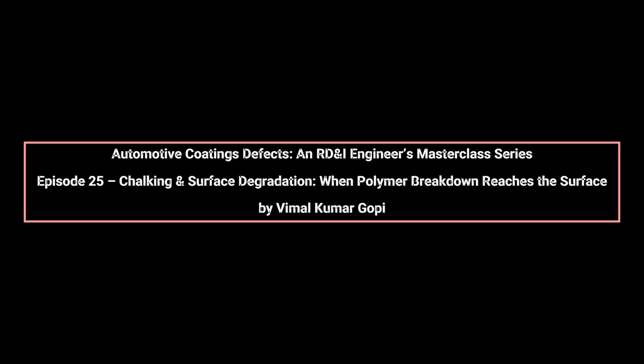Once chalking begins, protection is compromised. The surface becomes porous, allowing rapid ingress of water and contaminants. At this stage, polishing can temporarily improve appearance by removing degraded material, but it also reduces remaining film thickness, accelerating future failure. OEM durability targets assume no aggressive polishing during service.